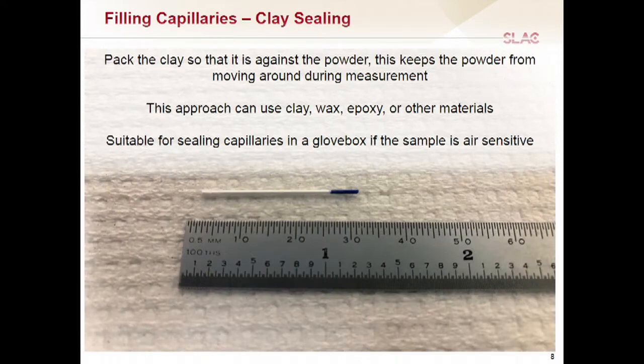So this is the end result. Sorry, in this case, the powder is white, but here's the end of the capillary. Here's where the powder ends, and then there's the clay plug. So again, I have roughly an inch of sample. This is a slightly thicker capillary. This is an inorganic molecule, so I can probably get away with that.